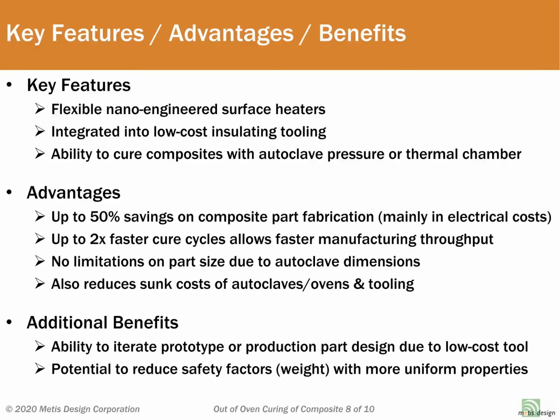So to summarize, we're using flexible nano-engineered surface heaters that can either be directly applied to the surface of a laminate or integrated into low-cost non-metallic tooling in order to conductively cure quality aerospace-grade composite parts outside of an autoclave or oven. The key benefits include up to 50% reduction in cost due to tremendous energy savings and a faster cure cycle that allows for better manufacturing throughput.